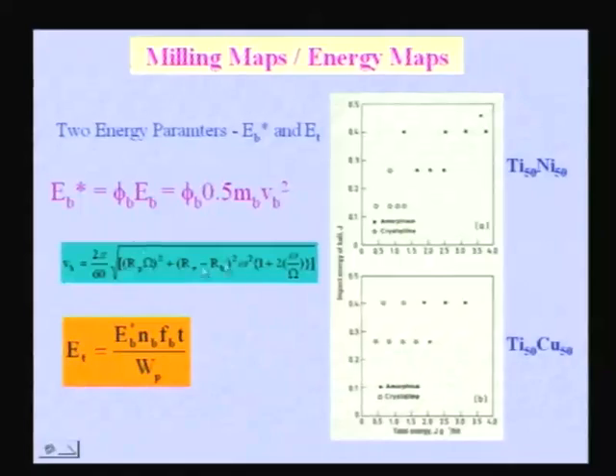So like that, one can put these two energy parameters and try to bring in all the milling parameters into these two energy parameters and look at what happens. When you plot these two energy parameters, y-axis the impact energy of the ball, x-axis the total energy, and try to see under what conditions you get an amorphous phase.